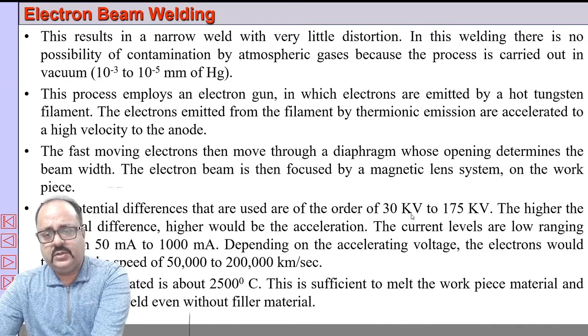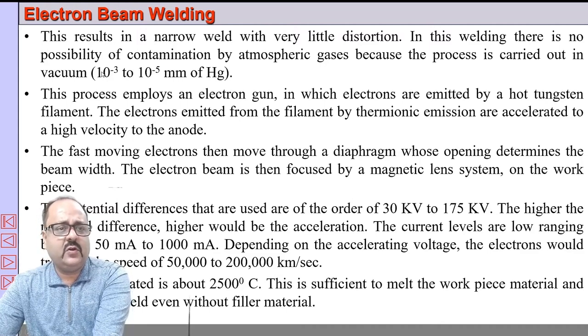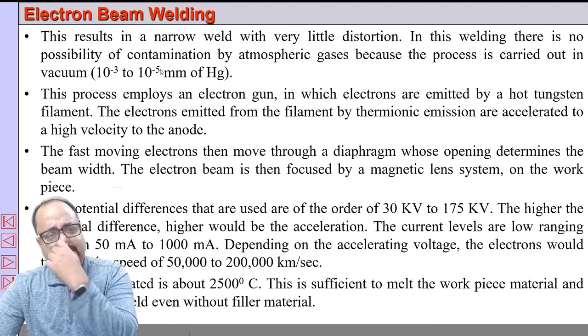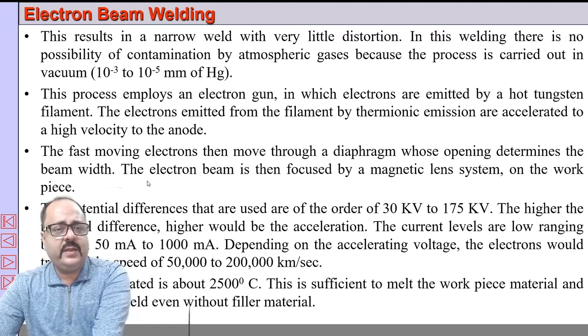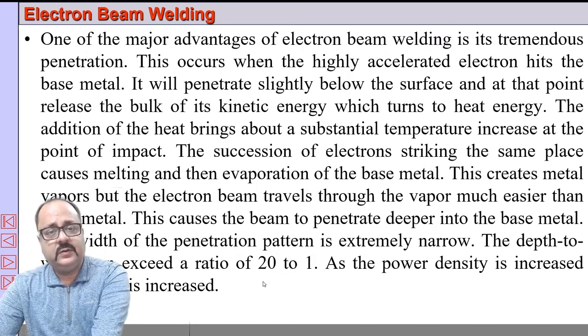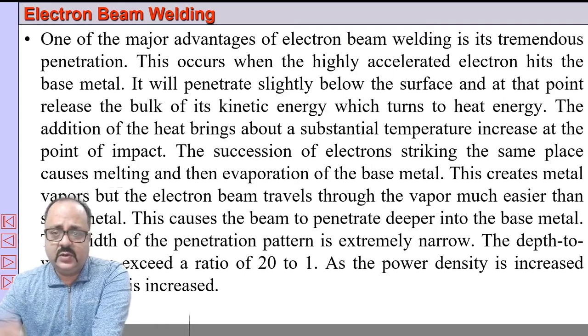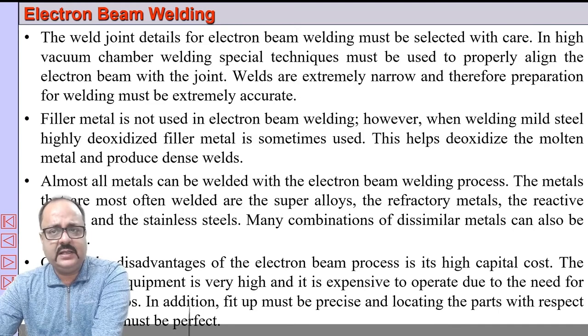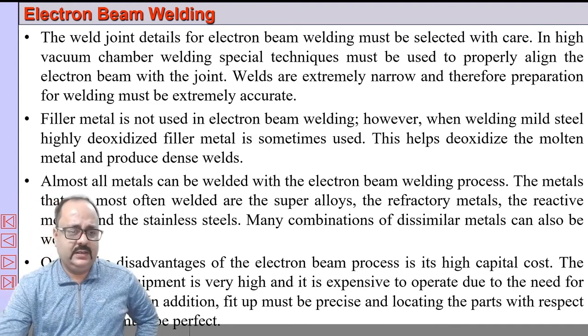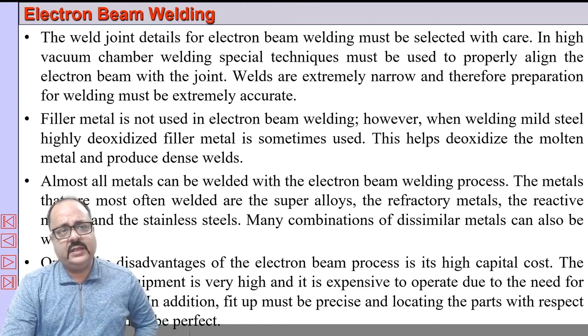The voltage ranges from 30 kV to around 175 kV or more — even up to 300 kV. The normal vacuum range is around 10⁻³ to 10⁻⁵ torr for medium vacuum, and high vacuum is around 10⁻⁵ to 10⁻¹⁰ torr. The current is very low, and the temperature generated is around 2500°C or more in a very small area. The depth-to-width ratio can exceed 20:1. This process can weld very thin plates — down to 0.2 mm — and very thick plates, up to around 300 mm.